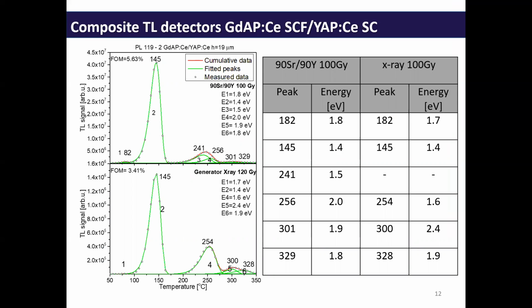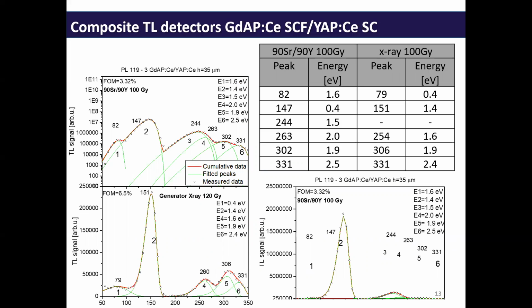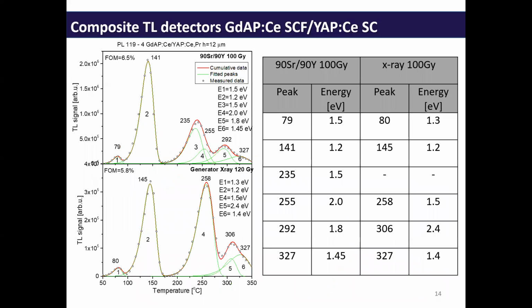In this part, we observe the different matrices of scintillator materials with the same type of activator, cerium-3+, using GdAP and YAP. The peak at 241 only occurs in the case of beta excitation. It is similar in the case of the sample with thickness 35 micrometers. It's worth paying attention to the intensity in the range 240 to 350 degrees Celsius, which is characteristic for the substrate. And we see the same situation in the last sample with thickness 12 micrometers.